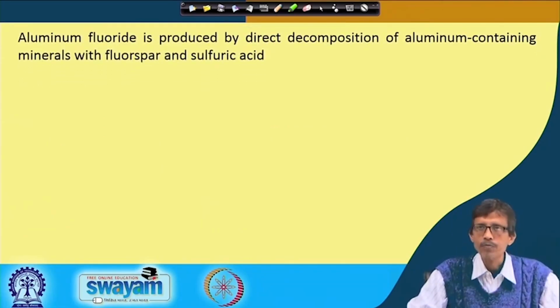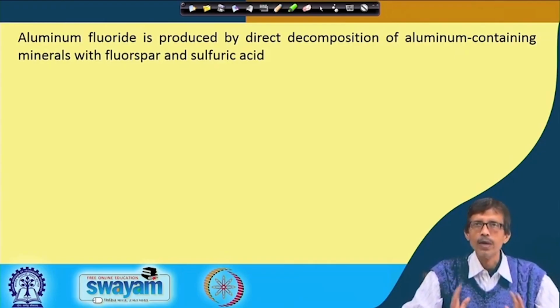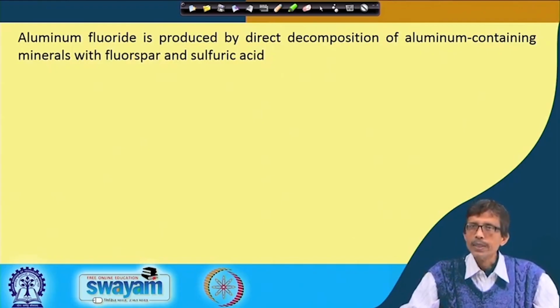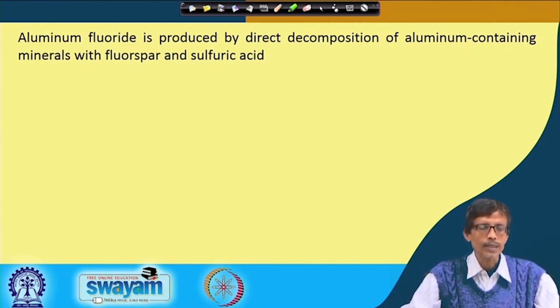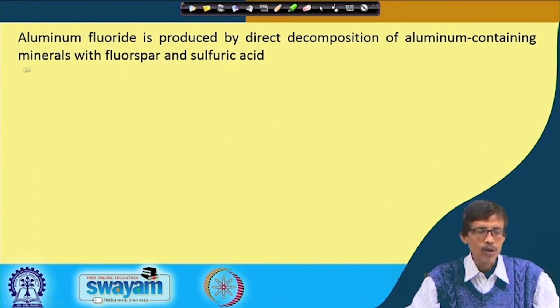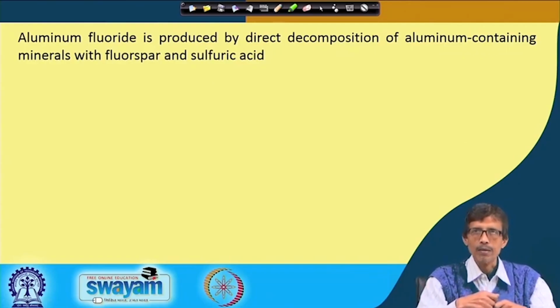So, we get that aluminum fluoride out of this calcium fluoride, simply converting the raw material, the ore. Typically treating the ore, that means the bauxite, the aluminum containing mineral, we have to decompose it. The aluminum containing mineral is nothing but your bauxite, and that bauxite is treated with fluorospar, that means calcium fluoride, and sulfuric acid. So, if we have a mixture, it can be at a very high temperature, because we do all these in industrial reactors, not in your test tube, not in your beaker, or not in your round bottom flask.